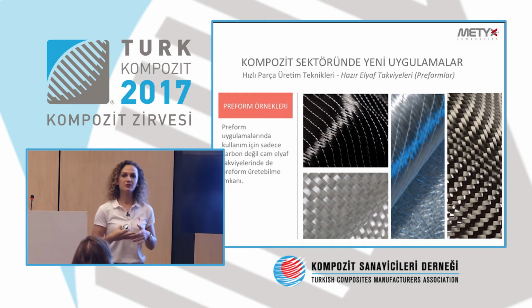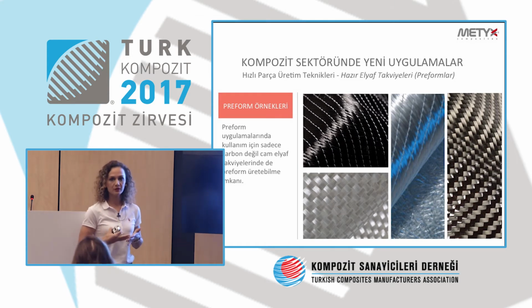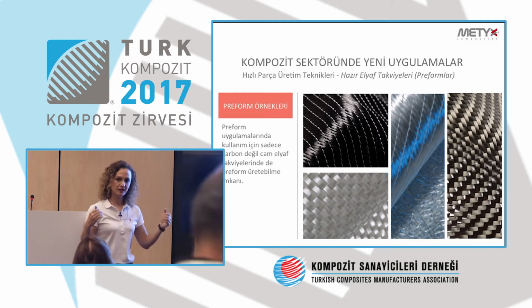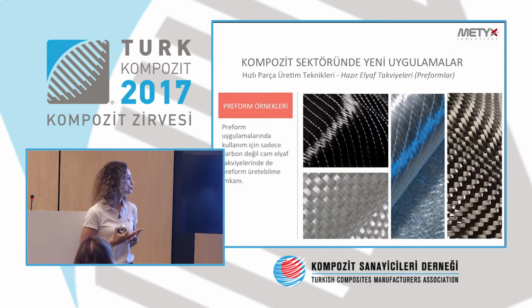Now we're trying to actually bring some certain solutions about this. We're not producing preforms, but we are producing fabrics that can form preforms, like multi-axials, could be carbon or glass. We are covering the material with the fabrics, and we take the fabric and put it into a hot press, and you can get the shape that you are looking for. So this is how you can get the preforms.